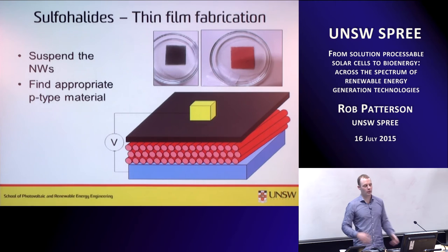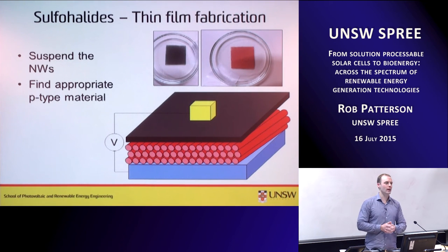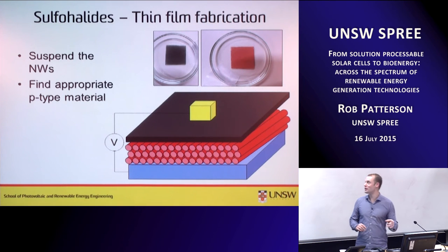So can we make thin films from this material? We can. The iodine on the surface is quite sticky. So when we spin coat these things, the material definitely coats the surface. But in order to make a good film, I've made these intentionally small.